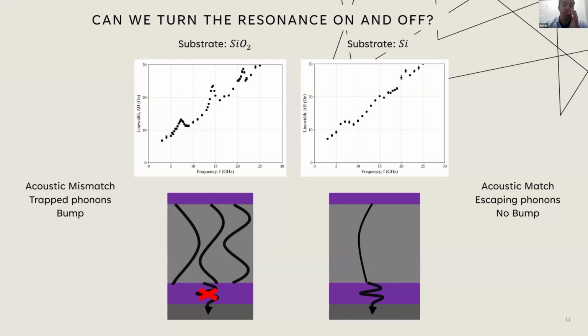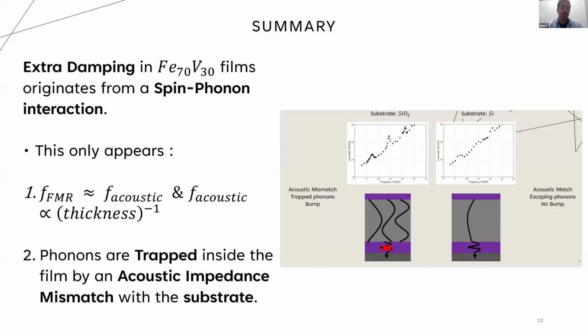The bumps vanish. Why? Because the silicon oxide substrate has an acoustic mismatch with iron vanadium, so it can trap phonons and we can see bumps. But if we replace silicon oxide with bare silicon, there is no acoustic mismatch, so phonons can escape and we see no bump. So in summary, we observed extrinsic damping in iron 70 vanadium 30 films originating from spin-phonon interaction.